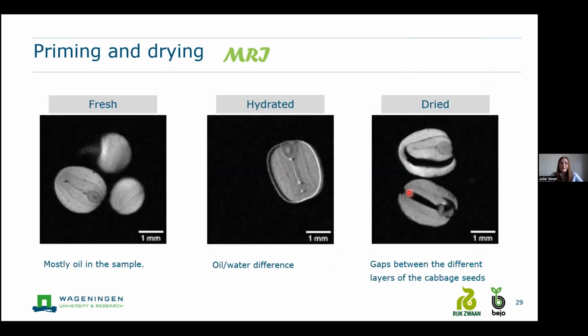For our samples, the first pre-trials look like that. So what do we see? First, we see fresh seeds, so basically dry seeds directly from the mother plant. Then we have hydrated seeds, and then dried seeds after the hydration. For the first one, we see a quite evenly distributed signal. So all the white spots indicate protons, and the whiter it is, the more protons are there. In our case, we assume it is water. However, oil also has a lot of protons and gives also a signal. And in our cabbage seeds, we have quite a lot of oil, around 30%. So we assume that in this dry seed, we mainly have oil, which we see here.